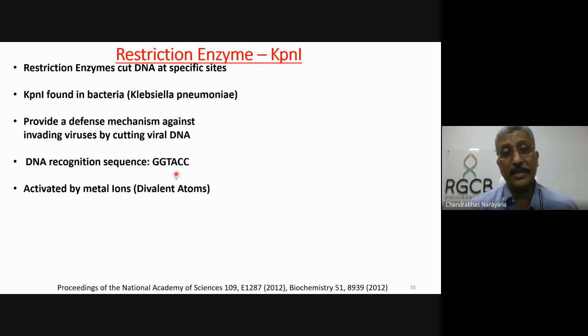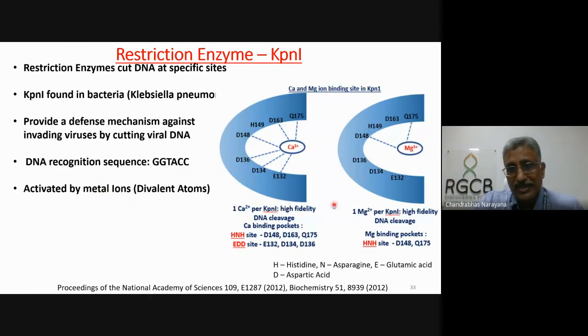Now, what they also found out is that if you change the metal ion, because these restriction enzymes have metal ions to get the tertiary structure, to put them together in a folded state, and that is very much dependent on what kind of metal ions are present. If you put calcium and if you put magnesium, the structure is quite different. And if the structure is different, its property is different.